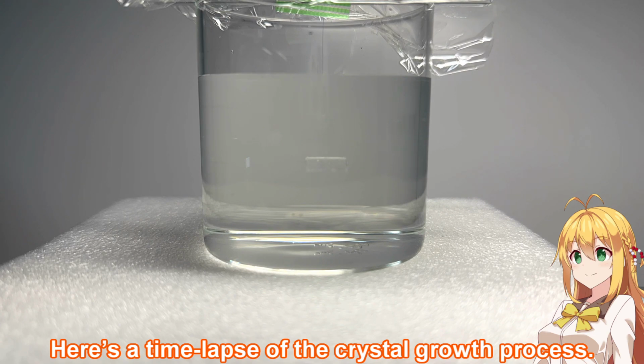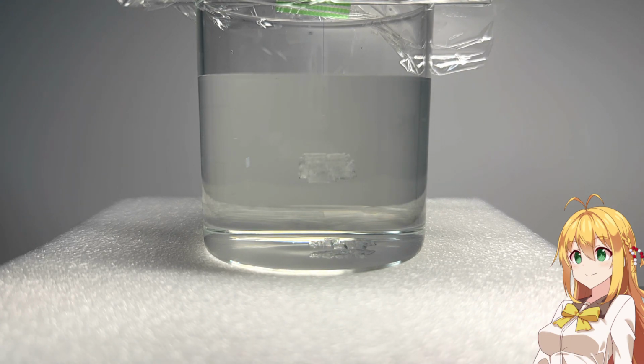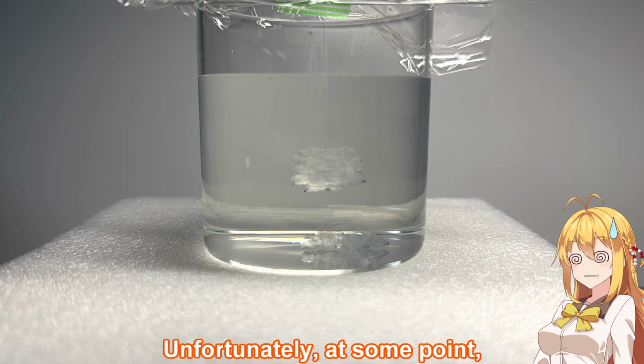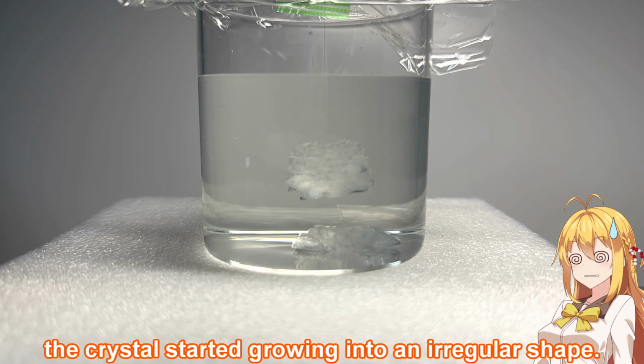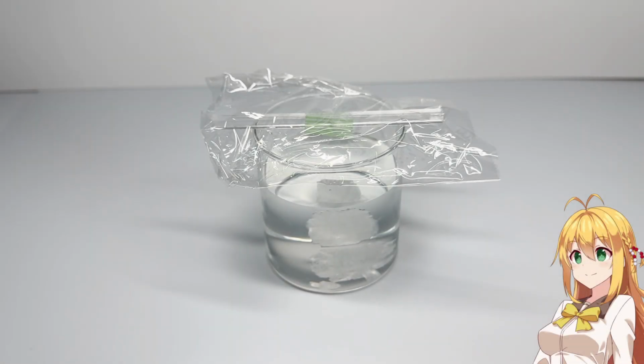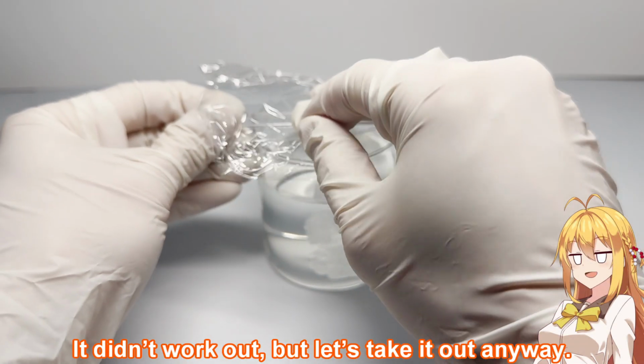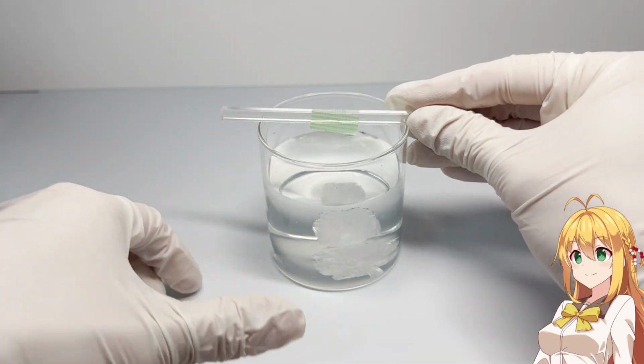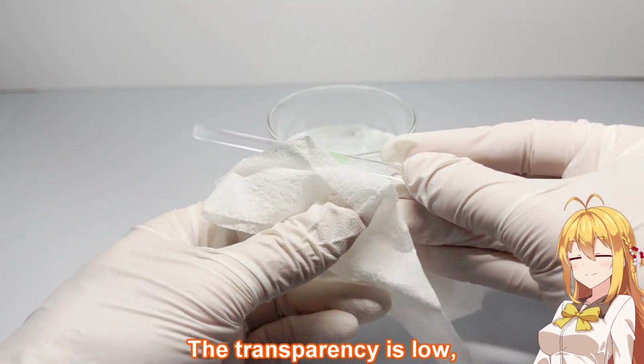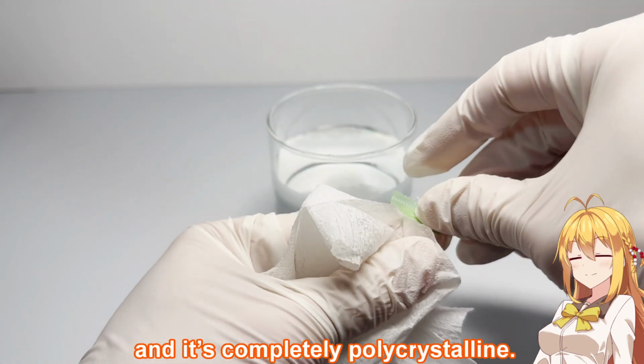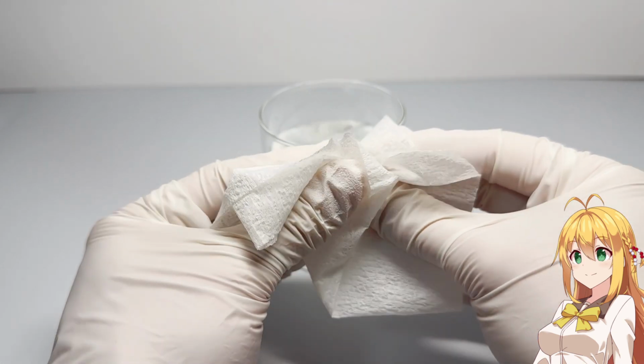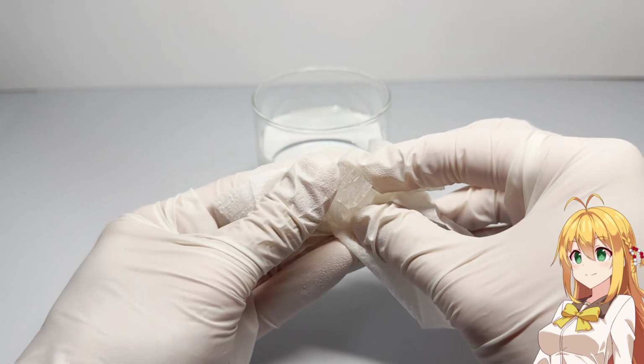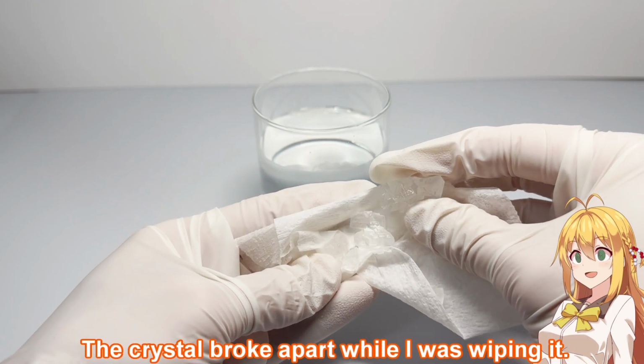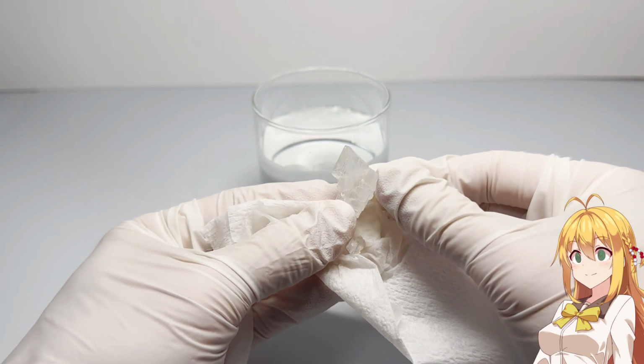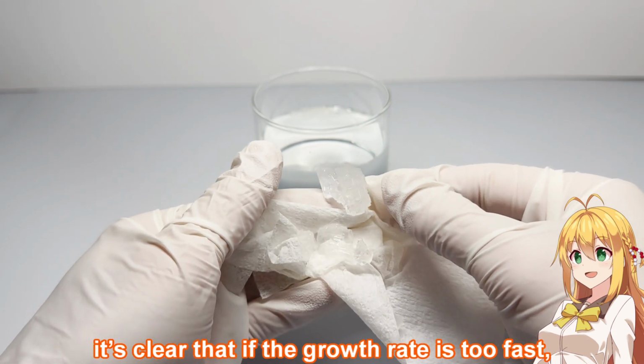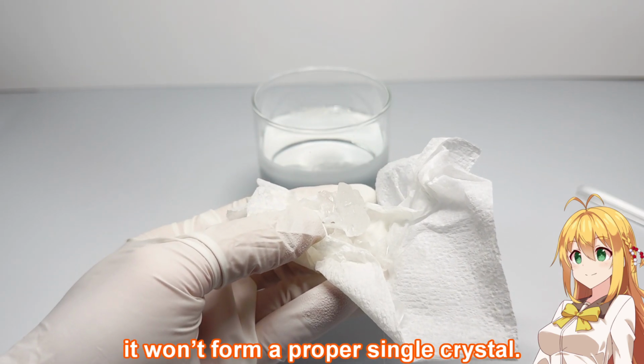Here's a time-lapse of the crystal growth process. Unfortunately, at some point, the crystal started growing into an irregular shape. It didn't work out, but let's take it out anyway. The transparency is low, and it's completely polycrystalline. Oh no! The crystal broke apart while I was wiping it. From this experiment, it's clear that if the growth rate is too fast, it won't form a proper single crystal.